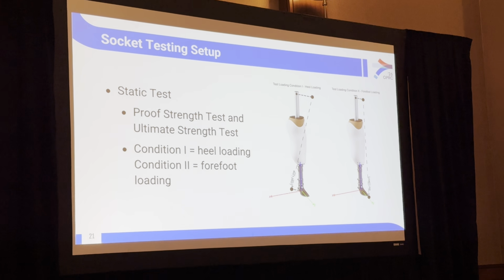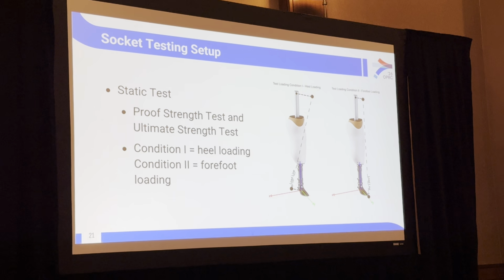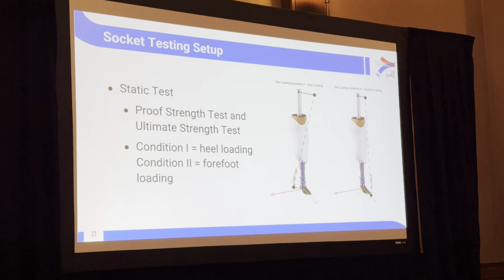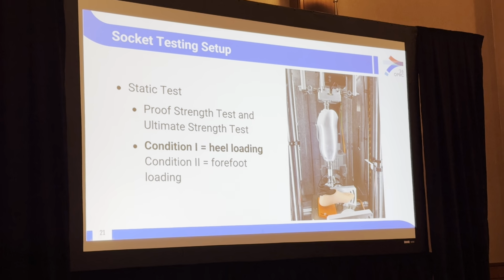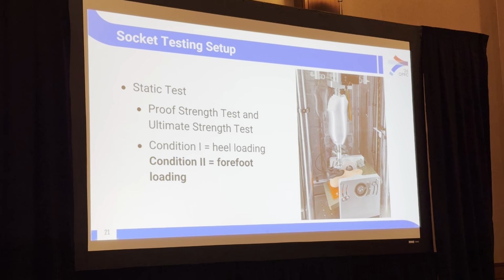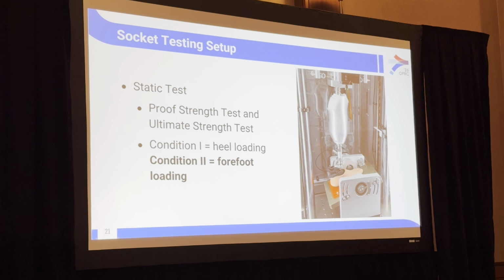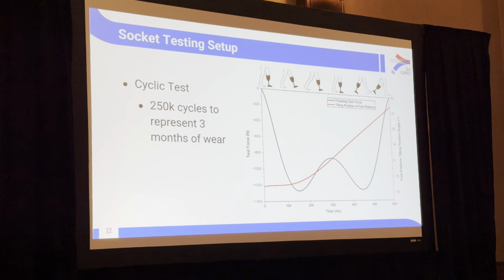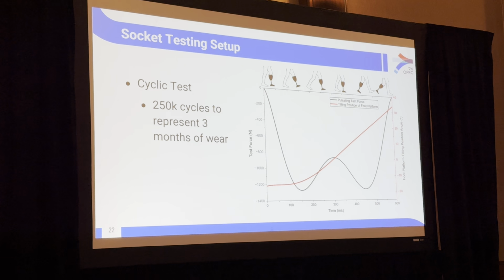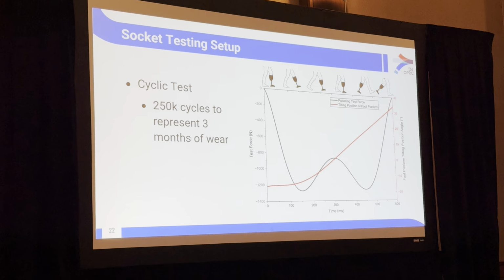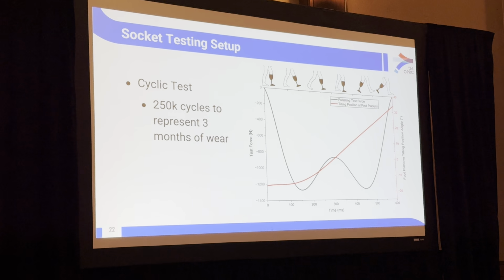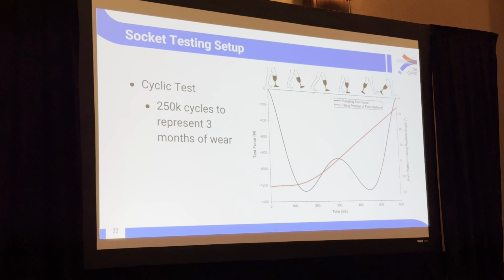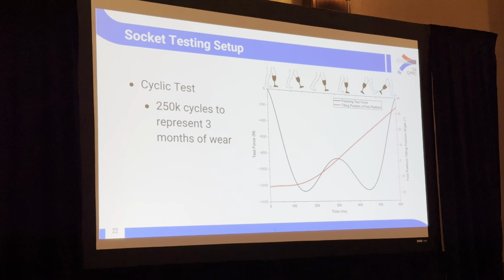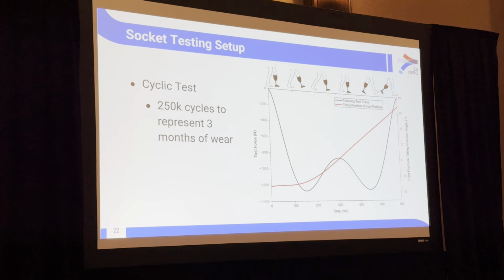So for the static testing portion, the standard includes proof strength tests and ultimate strength tests for 2 loading conditions. And so the first condition represents heel loading, and the second condition represents forefoot loading. For our cyclic test, we use a prescribed loading profile as well as a prescribed profile for that tilting axis position in order to represent and simulate a step. For our testing, we performed 250,000 cycles, and that was to represent roughly 3 months of wear, roughly the amount for what would be for a trial socket.